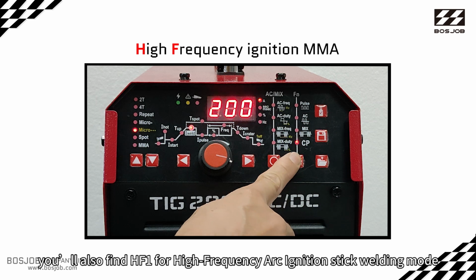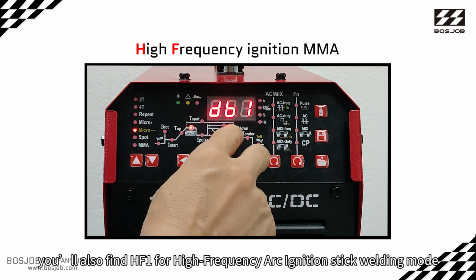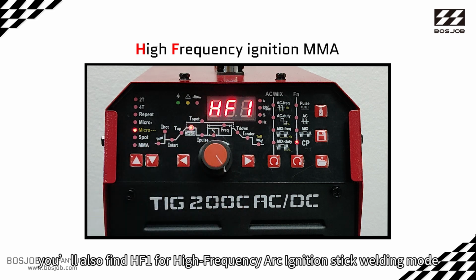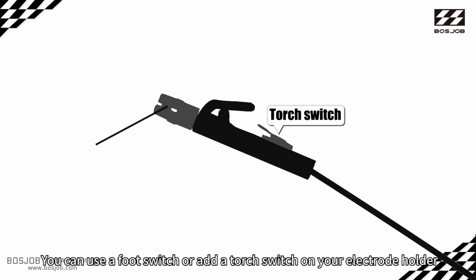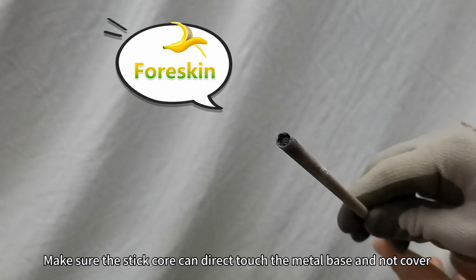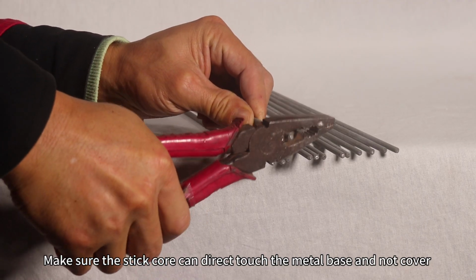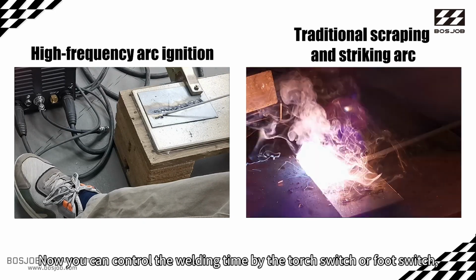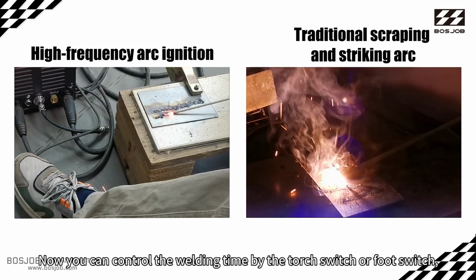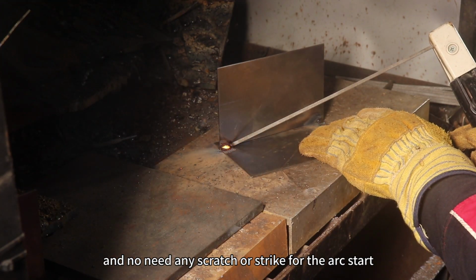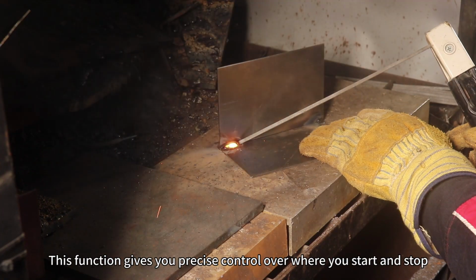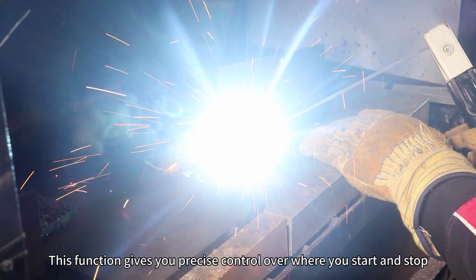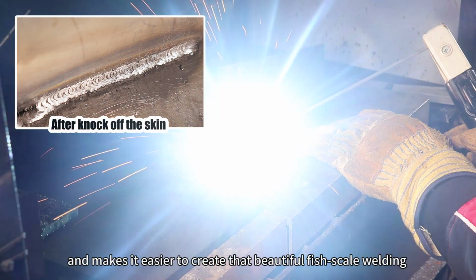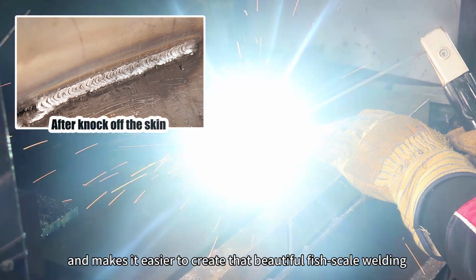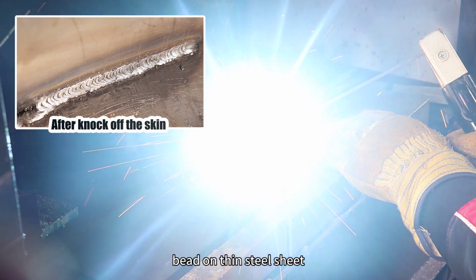In CP mode, you will also find HF1 for high frequency arc ignition stick welding mode. You can use a foot switch or add a torch switch on your electrode holder. Make sure the stick core can directly touch the metal base and not be covered by the coating. Now you can control the welding time by the torch switch or foot switch, and no need for any scratch or strike for the arc start. This function gives you precise control over where you start and stop. It makes it easier to create that beautiful fish scale welding bead on thin steel sheet.